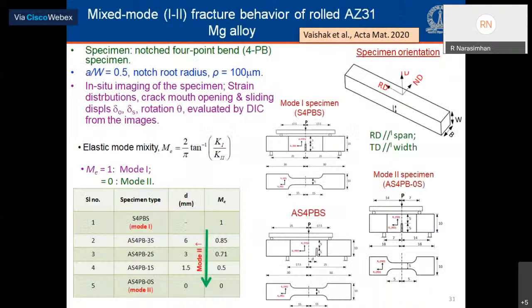Now let me spend a few slides on some very recent experiments which we have done on mixed mode fracture of magnesium, and this was conducted again with 4-point bend specimens with the rolling direction along the span, TD along the width of the specimen and ND along the thickness. So the characteristic specimen geometries are shown on the right side. In the symmetric 4-point bend specimen, the loading and support rollers are placed symmetrically with respect to the midplane.